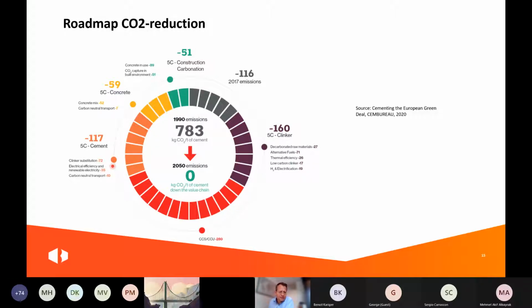cement itself, but of which 72 of clinker substitution. And that includes these alternative binders, but also replacement by slag and fly ash, limestone and burnt clay and other alternatives. So it is already explained that it will be difficult to find alternatives for regular Portland cement clinker.